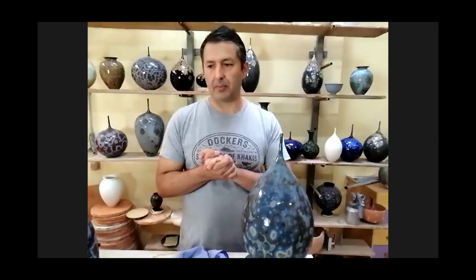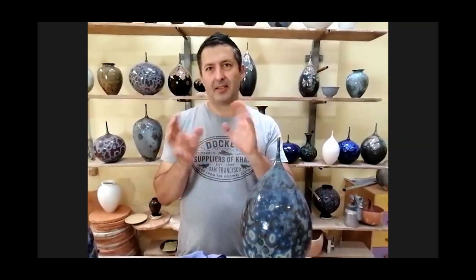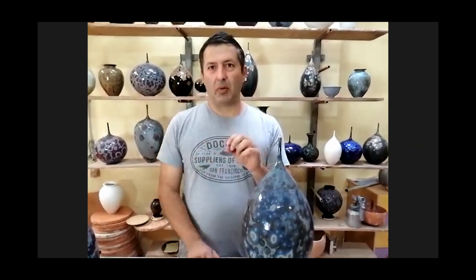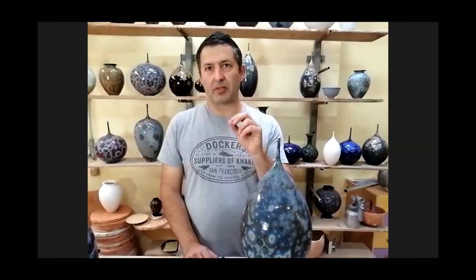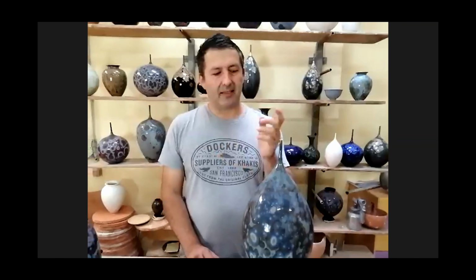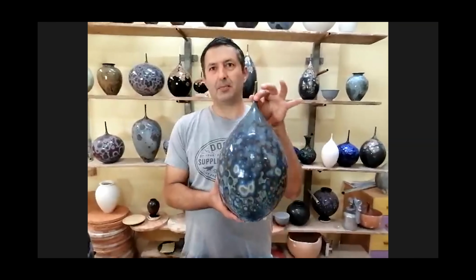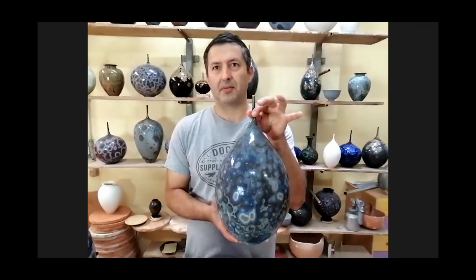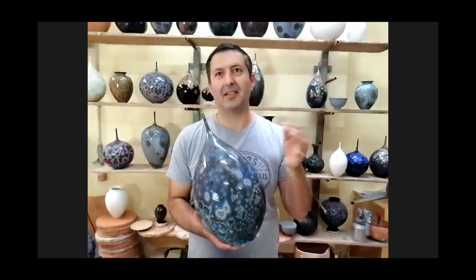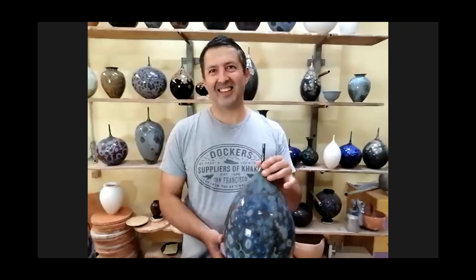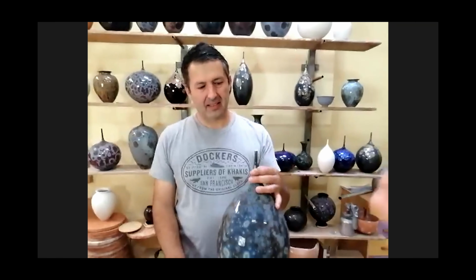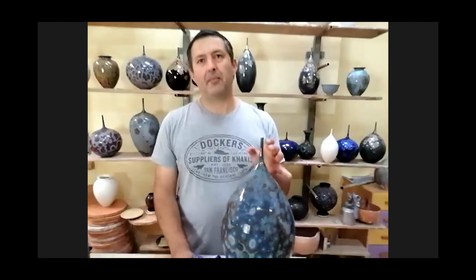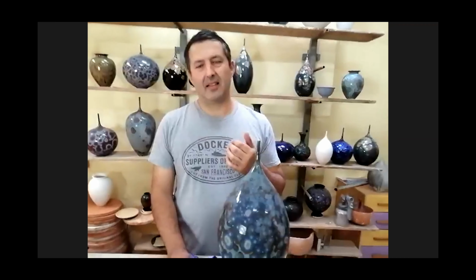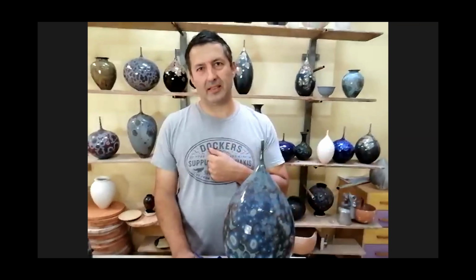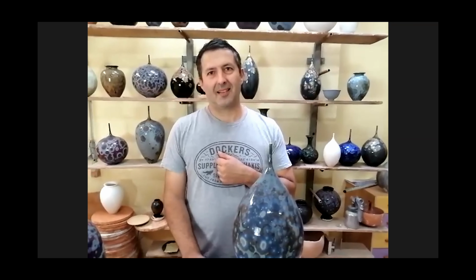Now you can see one PowerPoint, and there are some things you must understand. In the PowerPoint, I say for the copper oxide for post-reduction firing, you must use 1% or less. But you can see this pot is a Galaxy glaze. This pot has 9 or 10% of copper. And maybe you don't understand. You say, why are you saying for a post-reduction firing I need only 1% of copper, but this recipe has 9%? Because, remember, you put this piece in acid, and the acid eats the copper.